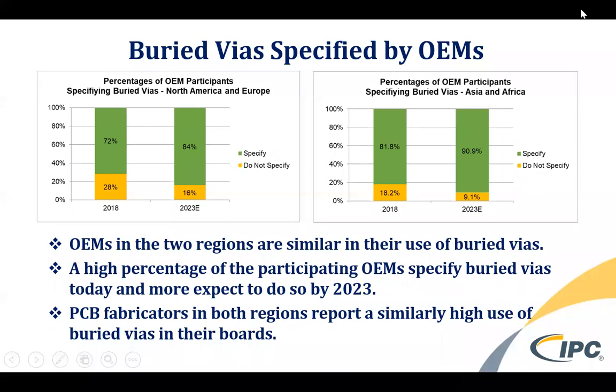When they do spec out these buried vias, they typically need to be filled. So they're either going to be filled with resin from the interlayer resin systems, or they're going to use different types of materials like polymeric paste, ceramic filled paste to fill those vias, and then create what they call overplating or overfilling of those vias. So that's an interesting technology that I'm sure will come out loud and clear in the full report.